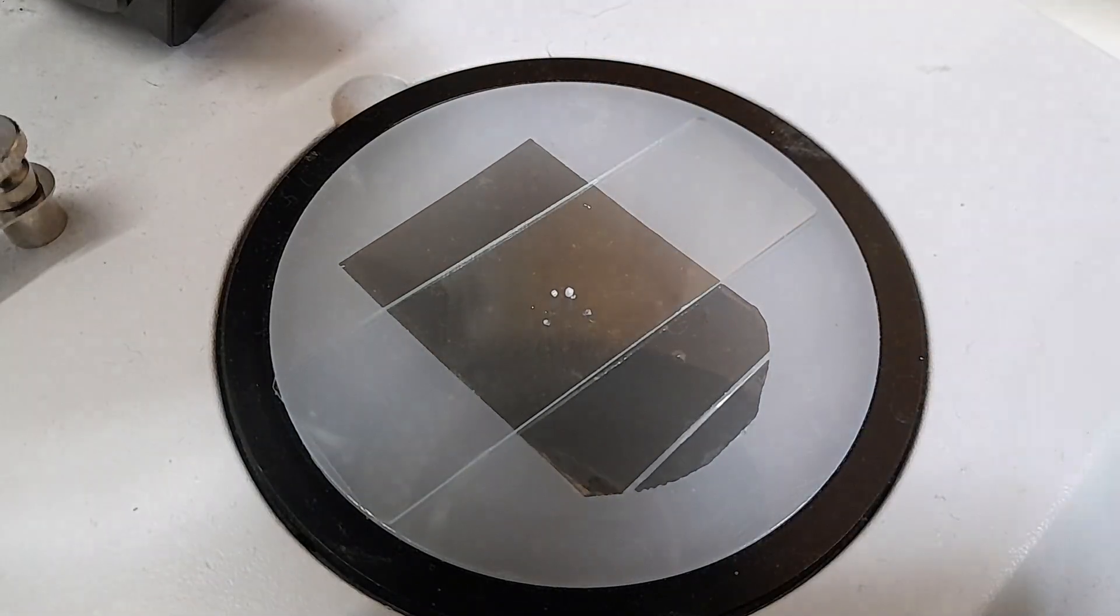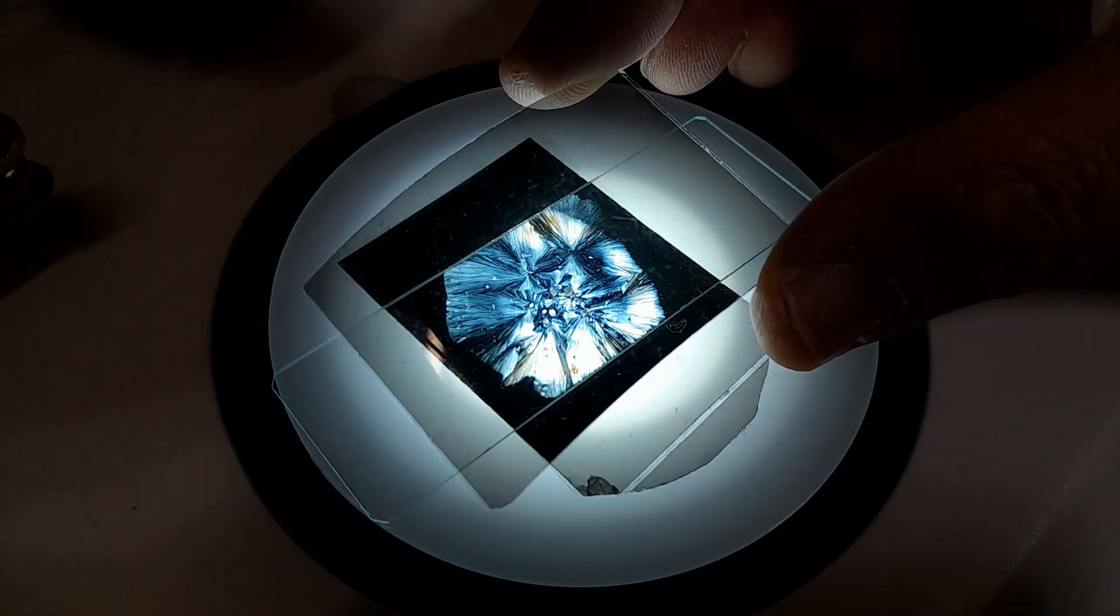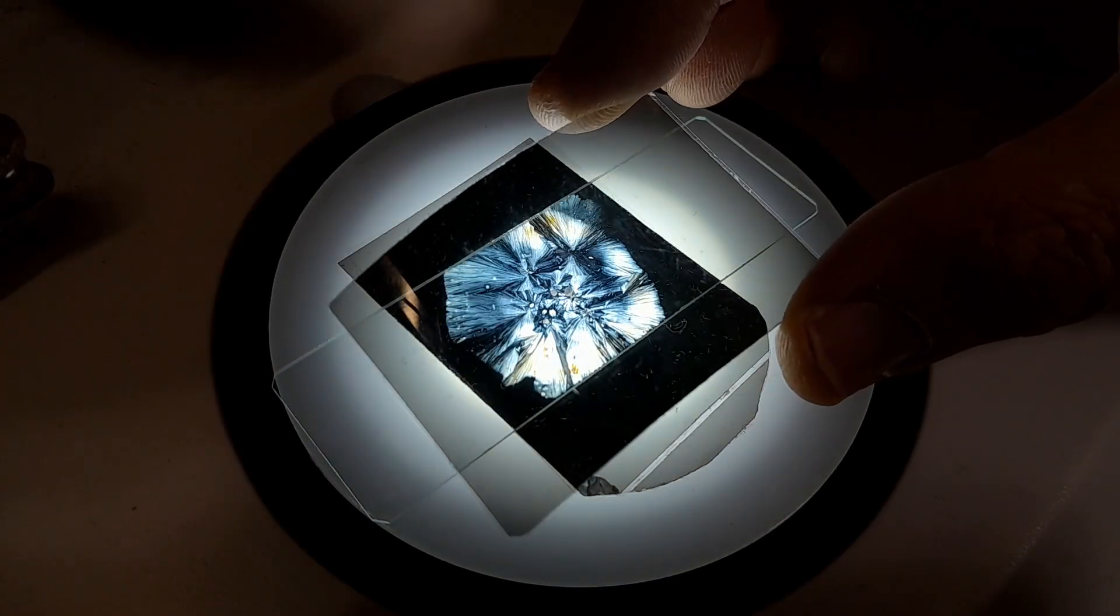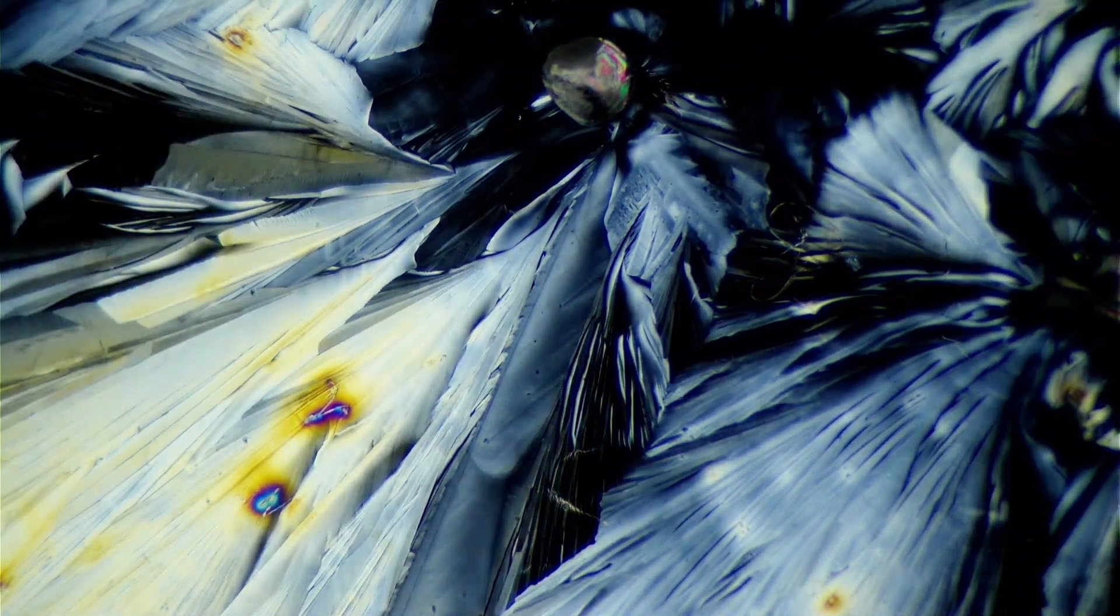And what you do is you take now the slide with your crystals and you put one filter, one polarization filter on the bottom, then you have the slide, and then you put another polarization filter on the top. And then what you have to do is you have to rotate one of those filters to get the best color display. And ideally you probably would like to probably roll them into so-called a crossed polarization position so that the background comes completely dark. And in the case of so-called circular polarizing filters, like for example some of those 3D glasses have, you might even have to flip one of the filters around to the other side because there is now, it's getting a little physical, there is a so-called wave plate, a lambda fourth plate also included, which makes it circular polarizing and then it is only on one side of the filters. I think this is getting a little too specific now. I think we're just going to forget about it. Just experiment around with it and flip some of the filters around as well and then you might also get different effects here.